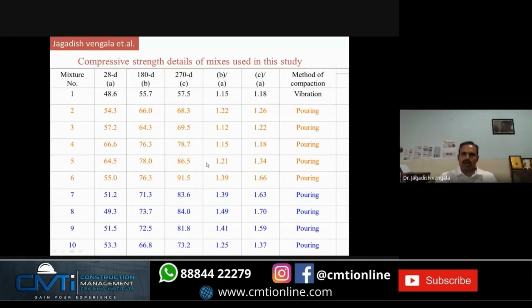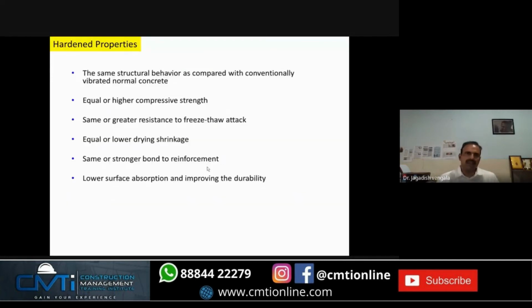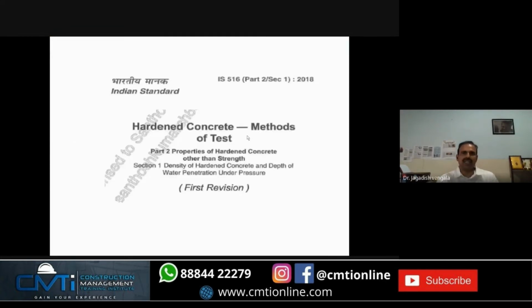So very interesting point here to note is when you make the mix, when you're pouring, you should not vibrate. Even if you're doing trials at your college, when you're pouring the concrete, you just have to pour. You need not vibrate because it is SCC. Hardened properties, yes, it almost gives equal properties to the normal concrete.